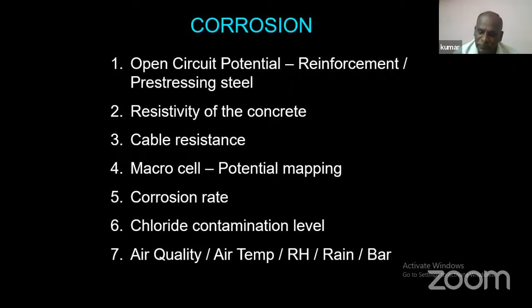Then corrosion rate measurement, that will give exactly how much corrosion is happening per year. Next is chloride contamination level. You can take a core of the concrete to the laboratory. We can check how much chloride has already contaminated. If you know the contaminated quantum of the chloride, then you can identify the corrosion rate, and you can identify the residual life of the structure.